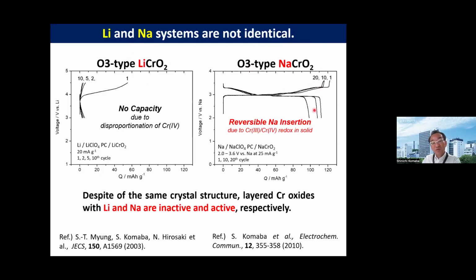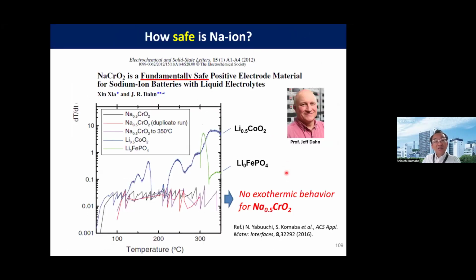In the case of sodium chromium oxide, several years later, Professor Jeff Dahn reported that sodium chromium oxide is a fundamentally safe positive electrode because, from their thermal analysis compared to lithium-extracted cobalt oxide and FePO4, heat generation is much, much lower for sodium chromium oxide. This is very good news for the safety of the sodium-ion battery.